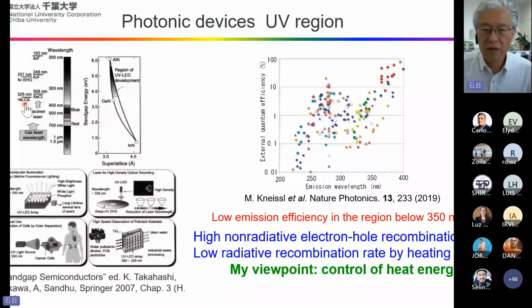this is the external quantum efficiency of the energy conversion from electric energy to photonic energy. This is a case of LED, and below 400 nanometers, the efficiency decreases drastically. And below 350, the efficiency is about 1% or less. So now for the hygiene application, 260 is desired, but in this case, less than 1%. This is a very severe problem.